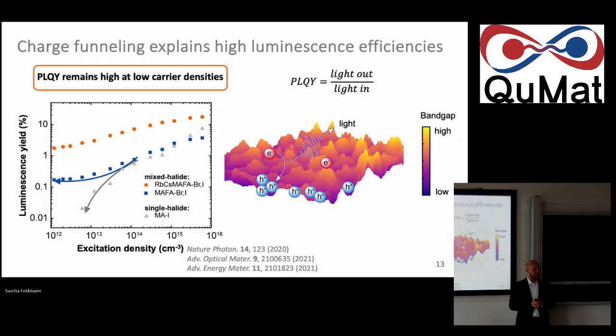Yeah. But these, let's say, local potentials, more charge carriers also affect Auger recombination. So they increase Auger recombination, which would lead to a little bit more non-radiative recombination. That's also true, but the Auger constants for these materials are such that we rarely enter that regime. That would come into play at 10^18 or so per cubic centimeter. Then yes, that would become problematic. But here we are so low, they don't really come into effect. And of course, yeah.